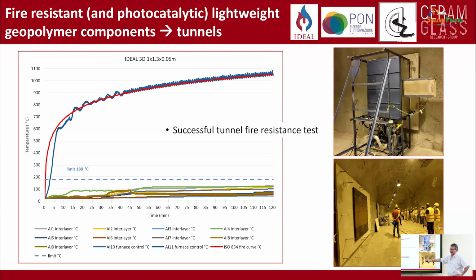And of course, you could say, well, why are you 3D printing something that is simply a sheet? But there are a lot of areas where you need curved structures. So additive manufacturing actually makes sense. And we tested both foams and 3D printed panels, and the 3D printed panels have better mechanical properties and better thermal resistance. The thickness of the board was 5 centimeters. We tried to reduce the thickness to 4 centimeters, but with 4 centimeters, you cannot keep the temperature below 180 degrees for as long as 120 minutes.